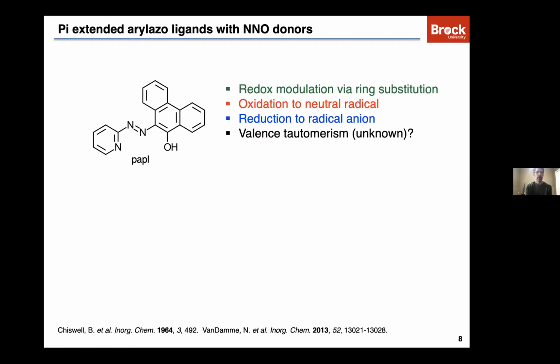So what types of ligands we're interested in are pi extended aryl azo ligands. Here's a typical example. We call this PAPL, and this is an NNO type donor. And there's lots of interesting features about these types of ligands in terms of their redox properties. You can modulate the redox behavior by substitution. You can oxidize it to a neutral radical, and you can, of course, reduce the ligand to a radical anion.